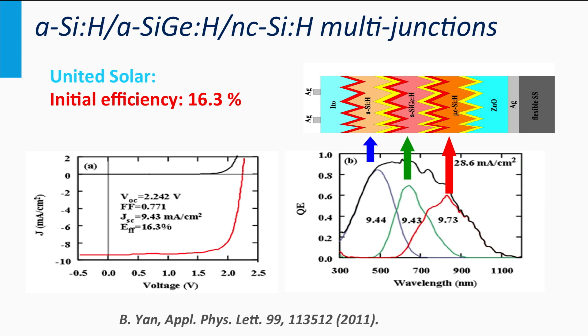In this figure you see the EQE of the three PIN junctions of a record triple junction of United Solar. The individual cells have various overlaps. They don't look like the block functions as we have seen for the III-V technologies. The light with wavelengths below 450 nm are utilized by the top cell only. Wavelengths at 550 nm are utilized by the top cell and middle cell. Wavelengths at 650 nm are utilized by all three junctions. Wavelengths above 900 nm are only utilized by the bottom cell.